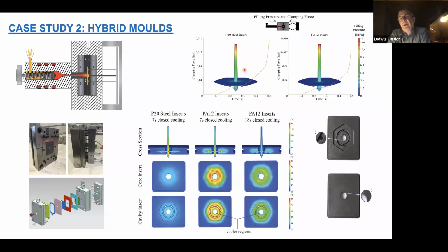But when you blend, for instance, what we did, polypropylene, polyamide, copolyesters as matrix material to improve their thermal conductivity, we blended them with a three-blend filler mixture of, let's say, on one side a very small amount of carbon nanotubes, on the other side flakes, and on the other side also spherical fillers. By blending them and having a good dispersion mixing of them, we improved from 0.2 up to, I think, 1.3 thermal conductivity. So that's, easy said, the tricky thing about that.